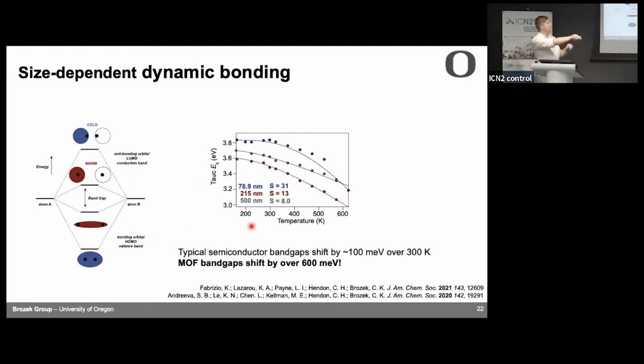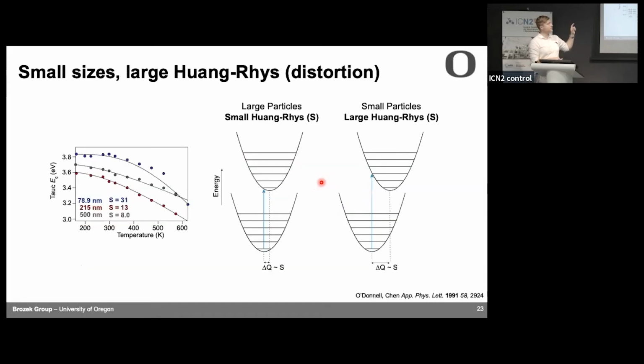We can do this for a variety of sizes with MIL-125. I'm plotting the optical gap versus temperature. We see that at a given temperature, the optical gaps are size dependent. That was unexpected. But then also how temperature dependent they are is strongly dependent on the size. In fact, the smallest particles are the most temperature dependent. If you heat them about 300 or 400 degrees, the gap shrinks by half an eV, which is really, really big. That's much bigger than in a typical semiconductor.